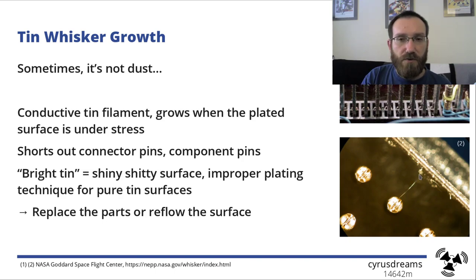You can almost not see them, so they're too thin to see with the bare eye, and what you do see is the light reflection of it. So if you want to look for that, take a light source, change the position, shine it on. And if you get something shiny that looks like dust, but it's shiny, maybe you have a tin whisker problem and you should replace the part, or you could try to reflow the surface, because that way you can melt the whiskers. They actually can carry a lot of current. It goes up to 70 milliamps that they can carry before they burn off.